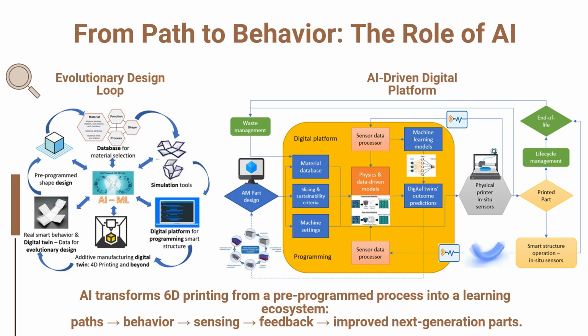Up to now, we've discussed how 6D printing allows us to embed smart behavior through our multi-axis toolpaths and smart materials, but the real transformation happens when we bring AI into the loop. On the left, you see the evolutionary design loop. We begin with a pre-programmed shape and material selection, but then we simulate how that structure behaves under different stimuli. The data generated from these simulations, combined with the real measurements from printed prototypes, feeds back into AI and machine learning models. These models learn which path geometries, materials, and interfaces produce the best functional results. This creates a continuous cycle: design, simulate, print, observe, learn, redesign. Each iteration improves the next generation of smart structures.